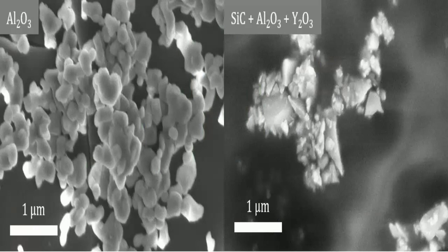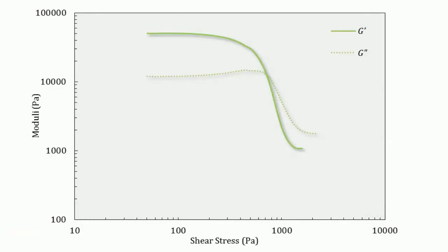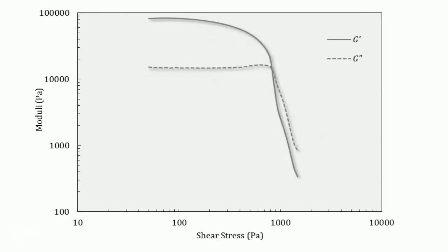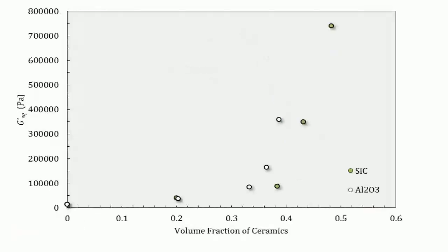They tried printing these monolithic parts in an oil bath, which is sometimes used for other structures, but it actually caused defects. That was a surprising finding for them. While printing porous scaffolds in oil can sometimes help support the structure, for these dense, solid parts, it seemed like the oil got trapped between the layers during extrusion, like little pockets of oil. Exactly, leading to defects, pores, in the final fired structure. It just shows you can't assume a process tweak works the same way for different types of parts or structures.